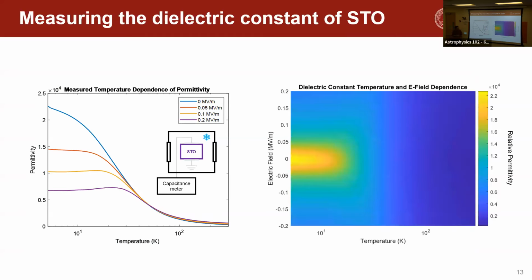And we can also probe this across our full phase space. What we see in these line cuts is a general increase of the dielectric constant as we go from around 100 Kelvin to 10 Kelvin, with the maximum being close to zero applied bias in our system.